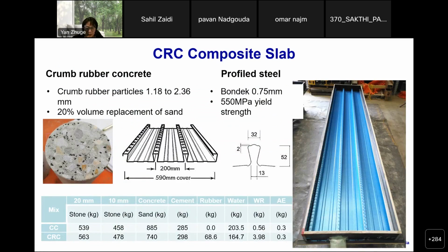After material properties had been extensively investigated, we conducted 2 projects to study the structural performance of crumb rubber concrete, where the strength requirement for concrete is not very high. So the profiled steel sheeting can work as a permanent formwork. That saves you money. You do not need to have formwork anymore during the construction process, and it can also safely carry the weight of the fresh concrete. So the target compressive strength for this testing is 25 megapascals.